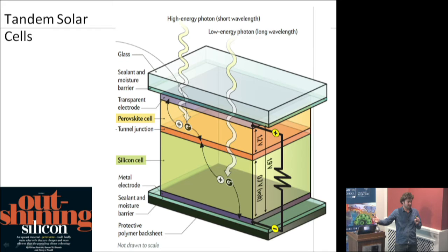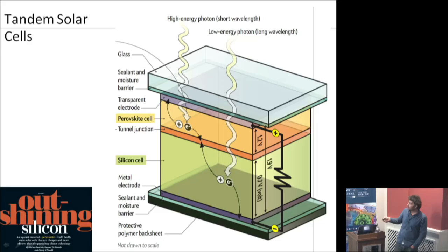And the solar cell can't generate any more voltage than the energy of light it absorbed. That would be disobeying thermodynamics. So if you have a single junction, a silicon cell that absorbs light down to 1 electron volt, you can never generate more than 1 volt from it. So all those photons are collected at 1 volt. If you can split that spectrum up into different energies, you can, for instance, collect the top section at 2 volts, and then you generate more power from that, and the bottom section at the lower voltage. So overall, going to multi-junction increases the efficiency, and the first step is to put perovskite on top of silicon.